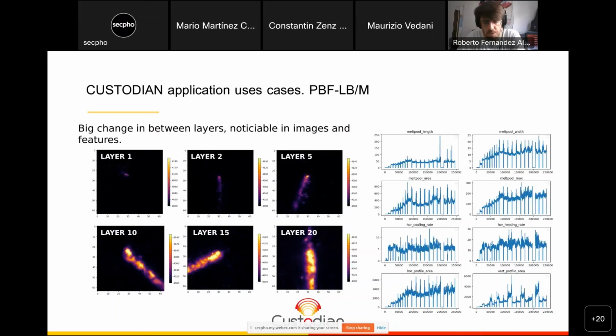This is a temporal analysis of the process. As we can see, while the layers are growing, the heat gets accumulated, because, depending on the geometry, the part is not able to evacuate the heat as fast as in the first layers. So the heat gets accumulated.